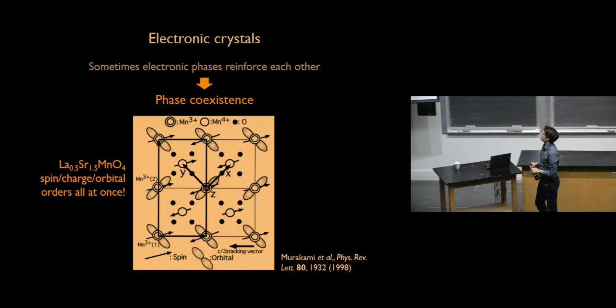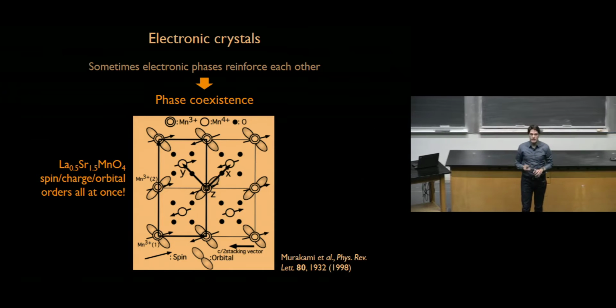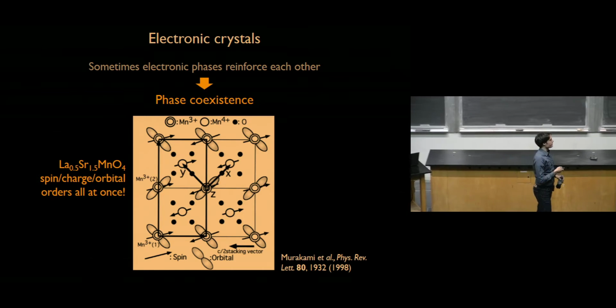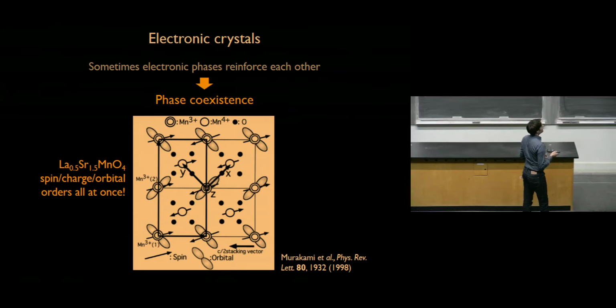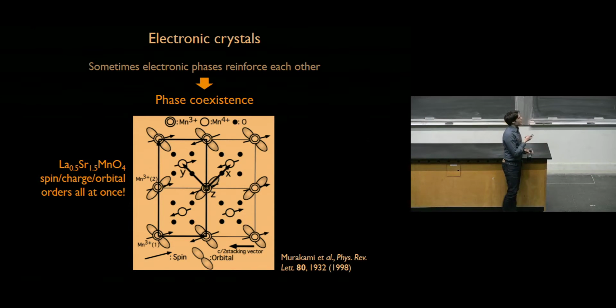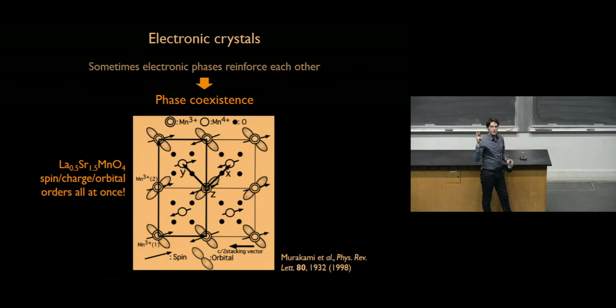Sometimes you have phase coexistence. So sometimes electronic phases reinforce each other. This is, again, the case of manganites. Manganites are a beautiful platform for this type of physics, by the way. And here you see three different electronic orders occurring simultaneously in the very same material. So in the very same spot in the phase diagram, a given doping and a given temperature, you have orbital order. So you see this alternation of these different orbitals. Sorry, these are actually d orbitals of the manganese.